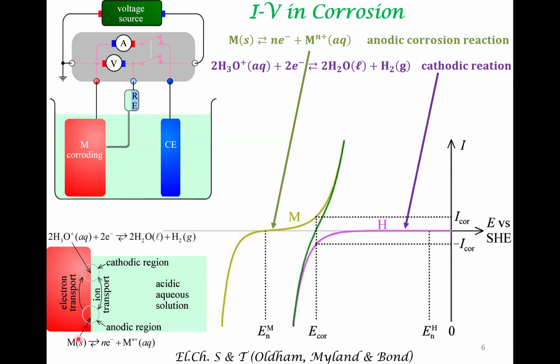That is, the anodic current should match the cathodic current if the potential of this metal is not going to drift. The potential at which the rate of generation of electrons via the anodic reaction matches the rate of consumption of electrons via the cathodic reaction is called E_cor. So this is the potential at which the net current is zero, and that is the potential relevant to corrosion of this metal.